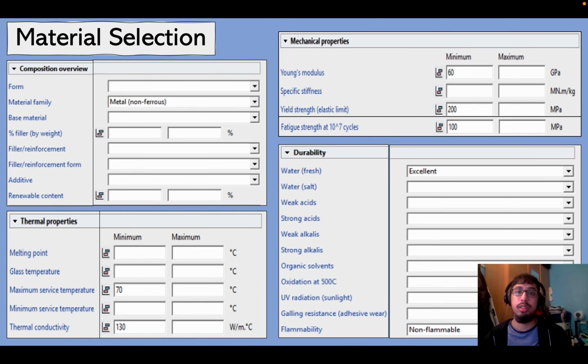We used CES EduPack to optimize for the ideal material. We made a few ballpark calculations to find the lower bound of the Young's modulus, yield strength and fatigue strength required, as well as inputting maximum service temperatures, humidity resistances, and flammability to screen unviable materials. Choosing only non-ferrous metals meant that materials wouldn't rust and wouldn't interfere with the battery's magnetic field, and after this screening, we are left with around 32 metals to choose from.